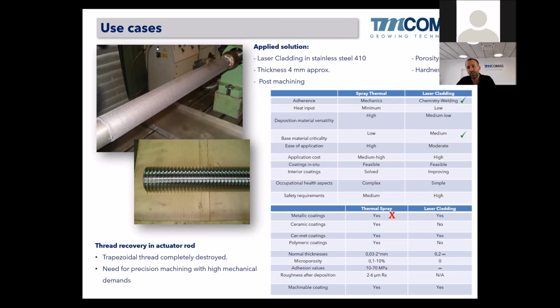We cannot machine a thread in a thermal spray coating. It is not welded, it is only mechanically there. So there is no option to have a high mechanical property coating that will withstand a thread. To machine a thread in a coating, you have to weld, so we used the laser to do that. Okay, so in this case, the thickness was about 4 millimeters, and then obviously we had to machine. We have chosen the laser because of the need of machining a thread afterwards.